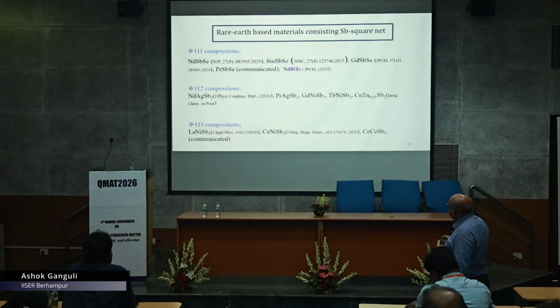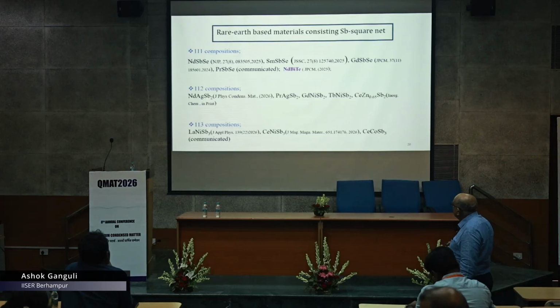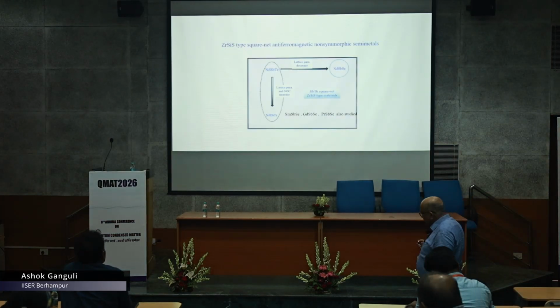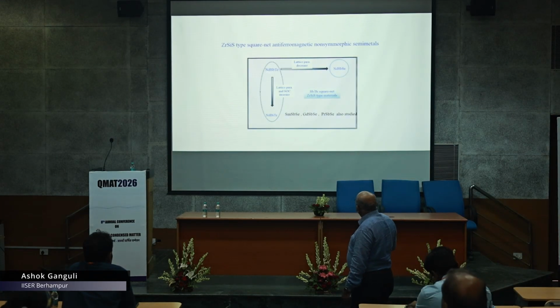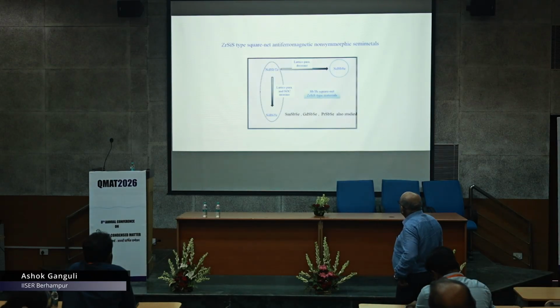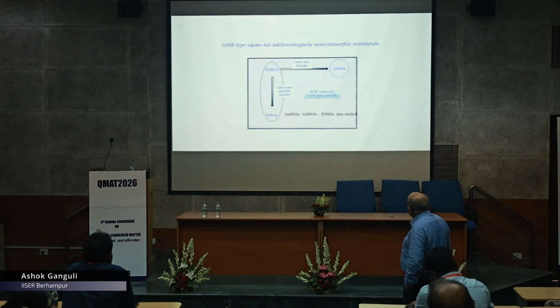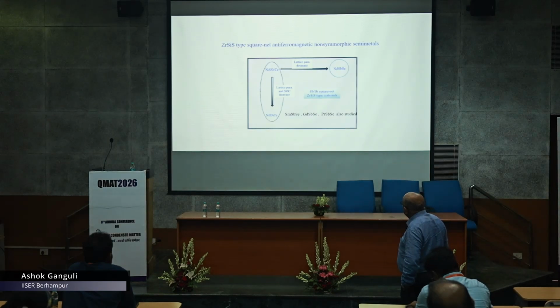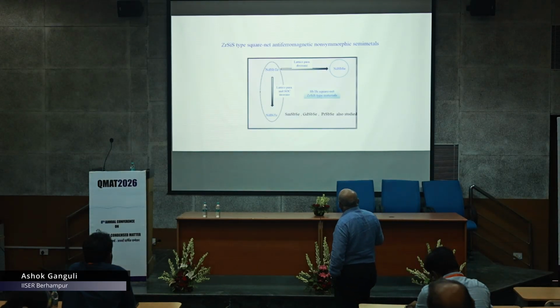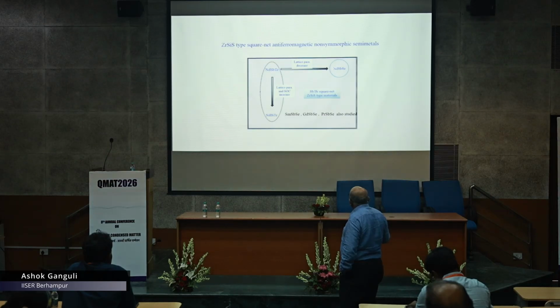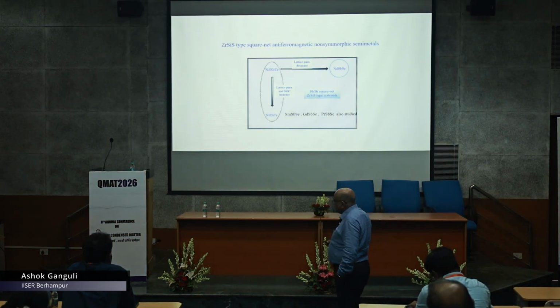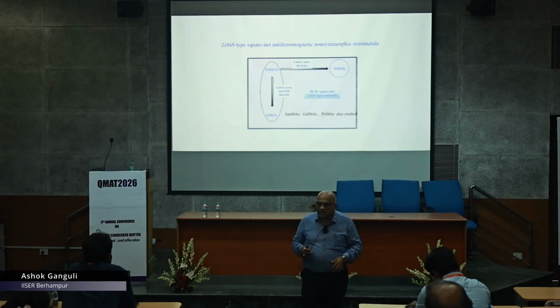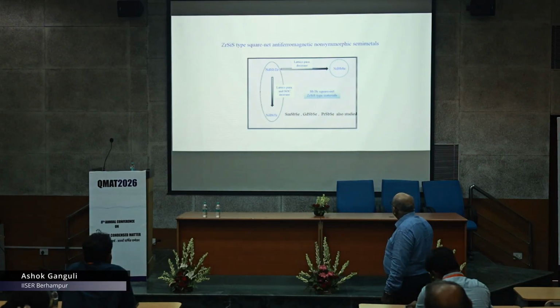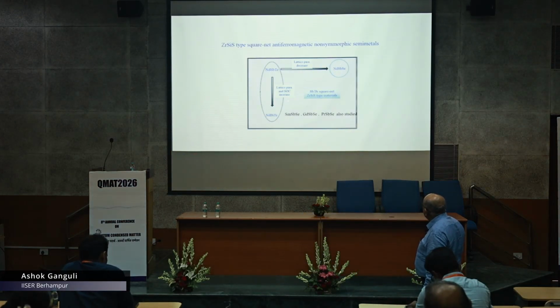So again, coming back, these are compounds we have published in these papers, 111, 112, 113. This was the starting point. We looked at this compound, and we tried to see that if we dope bismuth on the antimony side, you can increase the spin orbit coupling. So that was the intention, and if you can add selenium instead of tellurium, then you can reduce the lattice size and you can increase lattice contraction. So these were the two starting points, and then we added more 111 compounds to this phase.